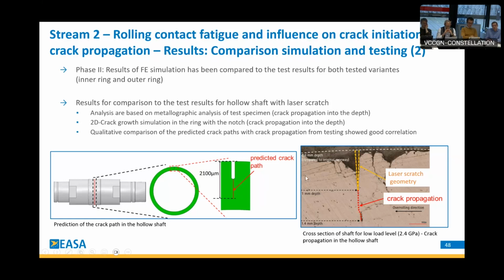And if we look at the testing, we also have the scratch. Of course, we have some surface damage here, but the crack propagation in the cross-section of the metallographic cut is showing it's correlating quite well to the expected direction.